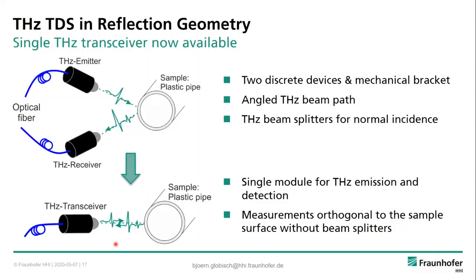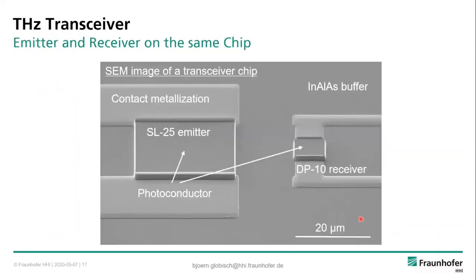It's quite fast. So one thing which is quite annoying still about terahertz measurements in reflection geometry is that we still use discrete emitters and receivers, and that makes reflection measurements quite hard because either you have an angled terahertz beam path or you need a beam splitter. And we're currently working on an integrated transceiver, so a single module that looks orthogonal to the sample surface without any beam splitters. And this is what we have been developing for 5 years now.